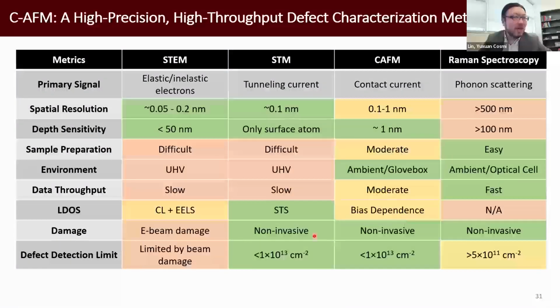Here is a rough comparison I came up with. We compare scanning transmission electron microscopy, STM, conductive AFM, and Raman spectroscopy. The electron microscope is also a commonly used method, and it can give you true atomic resolution. The major drawbacks are that sample preparation is a little tricky, the data throughput is slow, and there may be e-beam damage. Whenever we image the atomic structure, keep in mind the electron beam may have changed something, so we needed to develop a lot of analysis and data extrapolation to accommodate that.